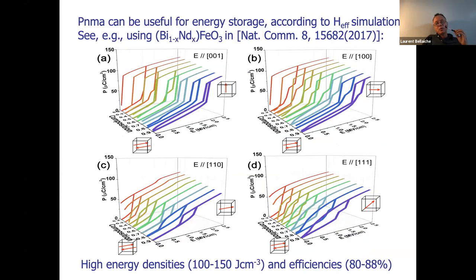And with that, we look, for example, at PNMA states in the bismuth neodymium system, in this paper done by first author Bin Xu. And we were able to compute polarization versus electric field. So you go from a PNMA state to a ferroelectric state. And this PE loop is very important because then you can compute energy storage, and you can compute efficiency, which is important for antiferroelectric applications. And we find huge energy density above 100 joules per centimeter cubed and very large efficiency. So we say, take a look at these antiferroelectrics, especially PNMAs, because they can be very promising for application.